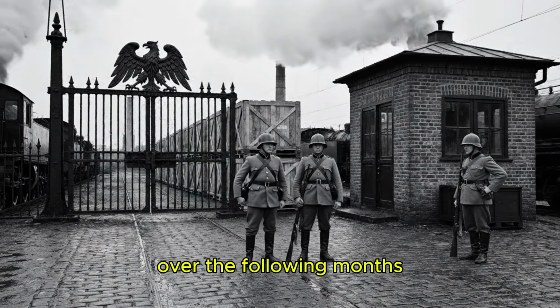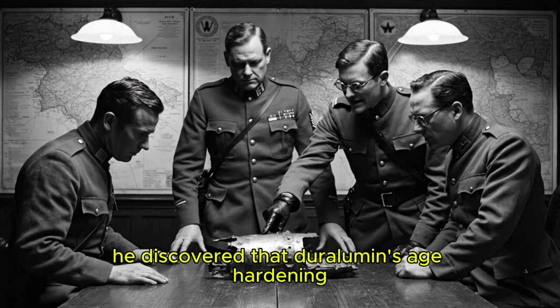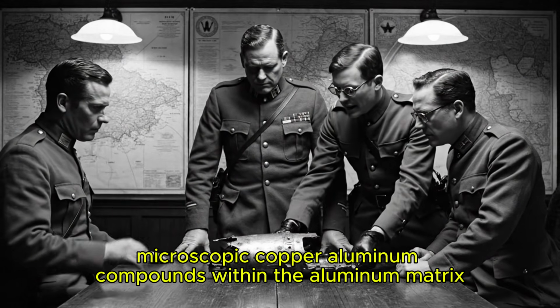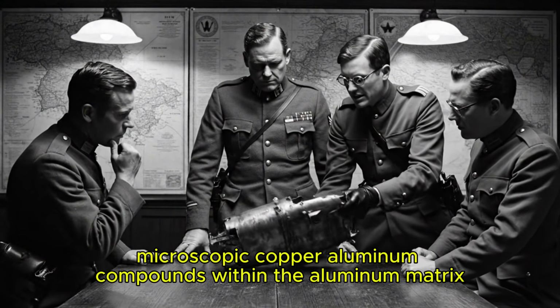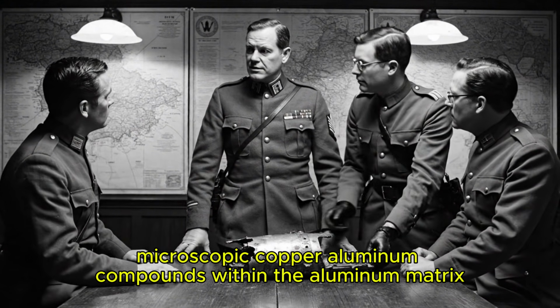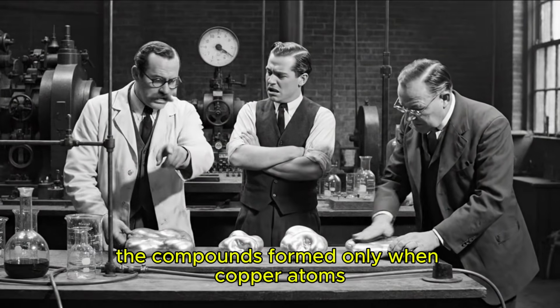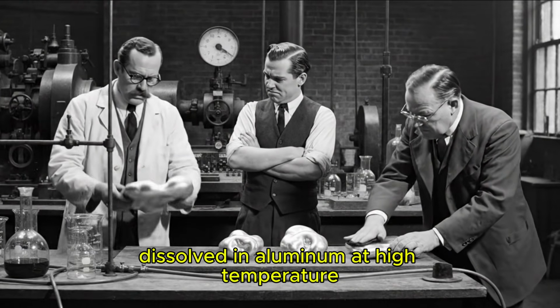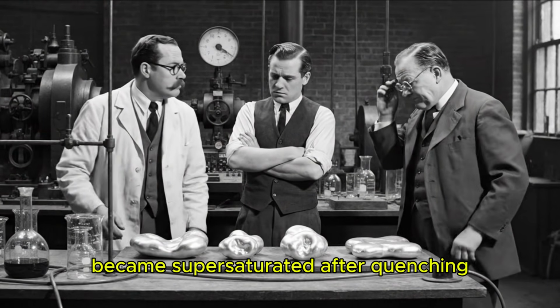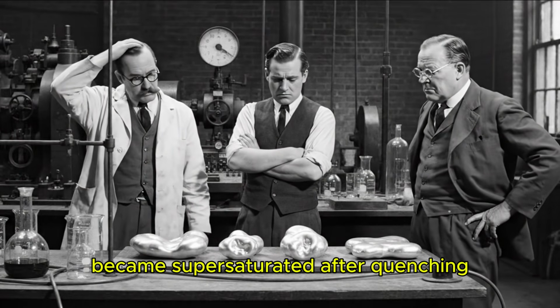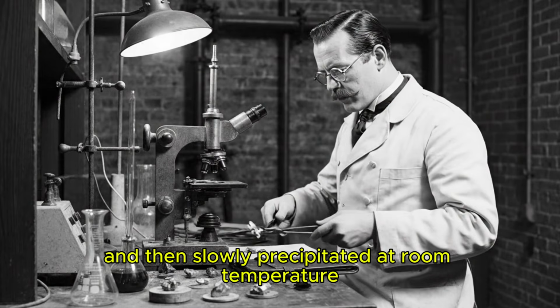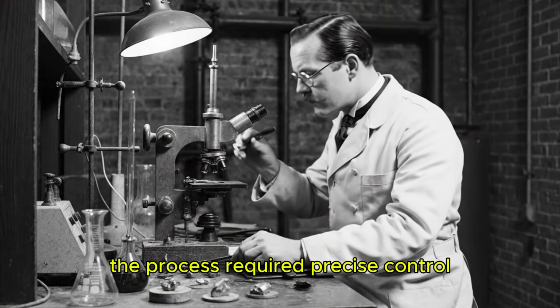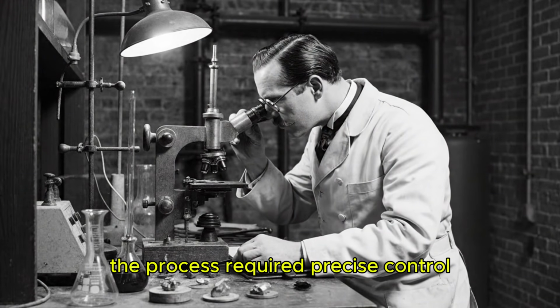Over the following months, he discovered that duralumin's age hardening depended on precipitating microscopic copper-aluminum compounds within the aluminum matrix. The compounds formed only when copper atoms, dissolved in aluminum at high temperature, became supersaturated after quenching and then slowly precipitated at room temperature. The process required precise control.